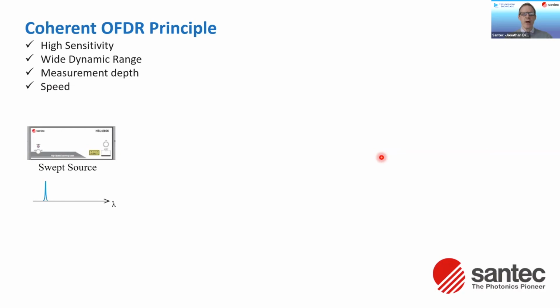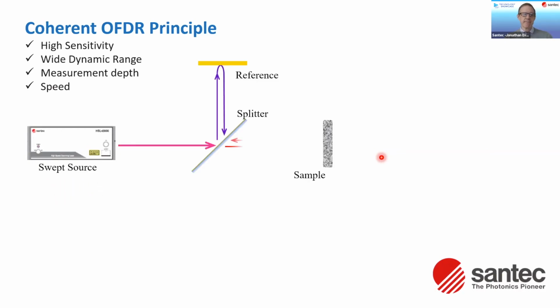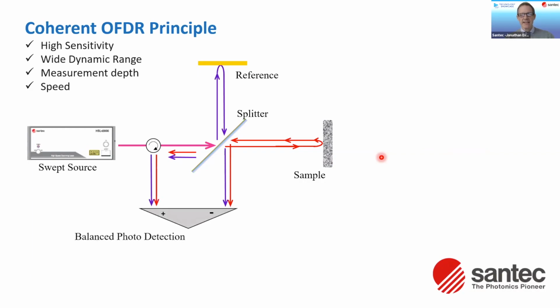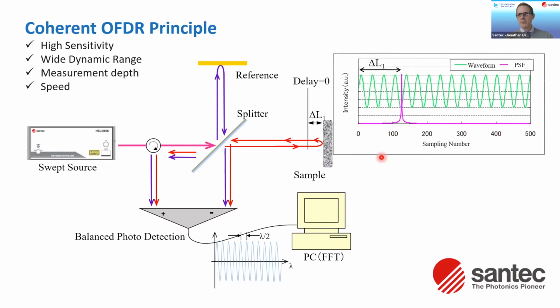So you can see it scans in wavelength versus time continuously. We send that signal to an interferometer containing a reference arm and a sample arm, whatever we're interested in measuring. These signals are recombined and detected on a balanced photodetector. So what we measure is an interferometric signal, but with FFT, we can derive the point spread function, the displacement of which is proportional to the position of the sample. So you can get a highly accurate measurement of the displacement of a surface using this technique.